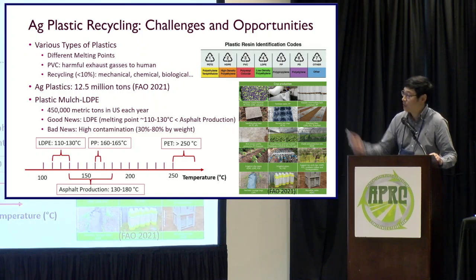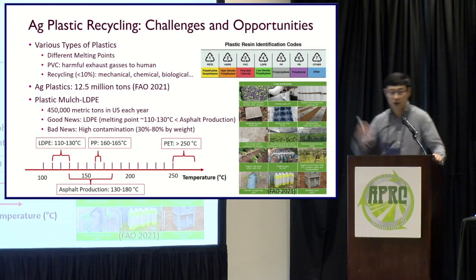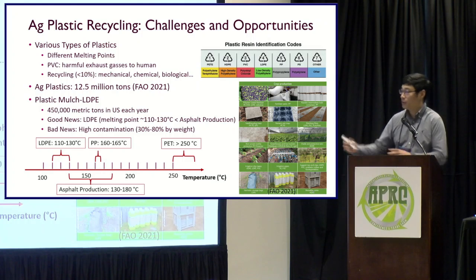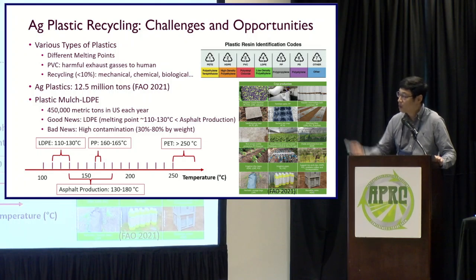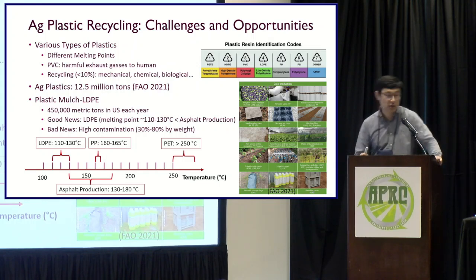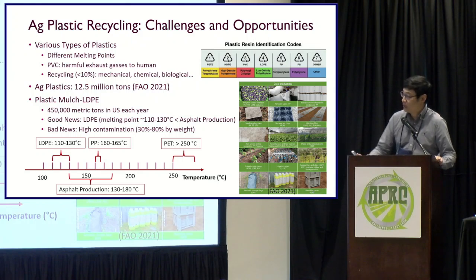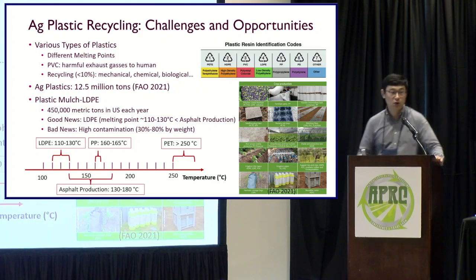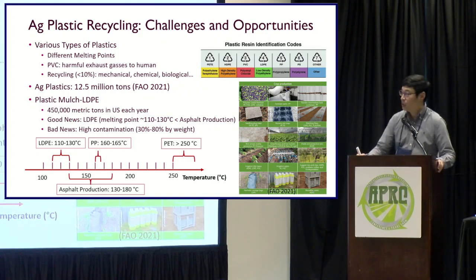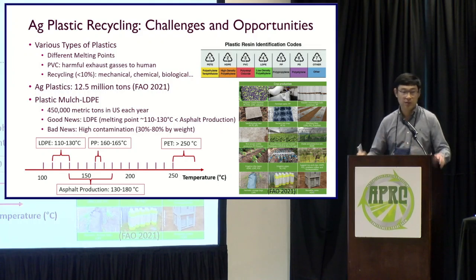And for ag plastic, based on the data, there are about 12.5 million tons used annually. So that's a big opportunity. We can do the recycling in different ways, especially we can digest some in the asphalt pavement. Talking about plastic mulch, the LDPE, annually in the US, there are about 450,000 metric tons generated. Well, the good news is for the LDPE, the melting point is lower than the asphalt production temperature. So when we blend the asphalt with the LDPE, the LDPE can be melted into the asphalt and used as a polymer.